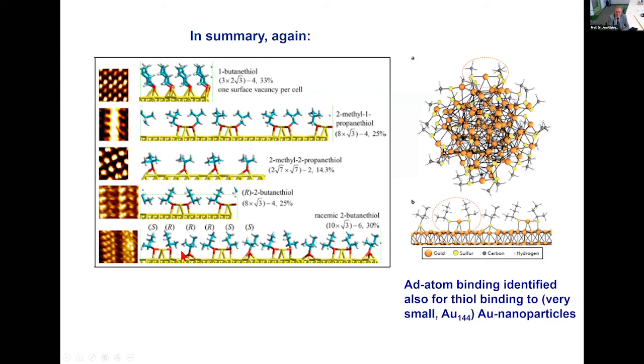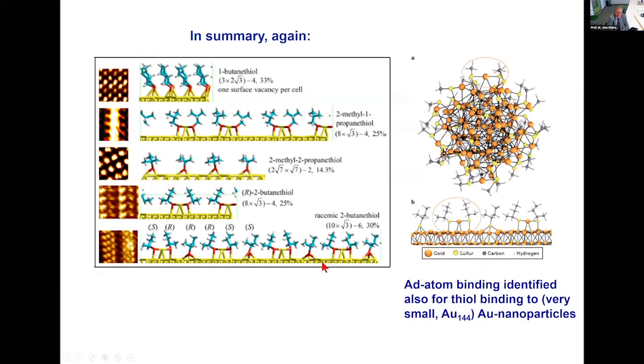again, as we saw for cysteine, they somehow are in each other's way, so they have to pack differently. Some of them are bound by the adatom mechanism, others, as you can see here, others directly on the surface. So here we have a case for the same molecule binding in two different ways on the same surface, and that is unusual. Some similar patterns are encountered if you go to nanoparticles. There are also adatom binding patterns.